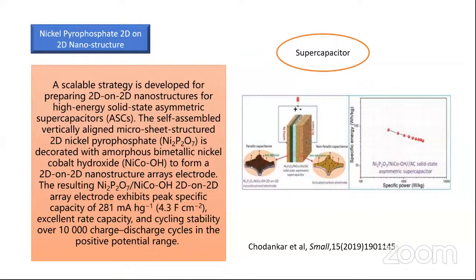The resulting nickel pyrophosphate, nickel cobalt hydroxide 2D on 2D array electrode exhibits a peak specific capacity of 281 milliampere hour per gram, and all these excellent capacities are given. And the cycling stability is over 10,000 charge discharge cycles. So this is a highly stable one, and it can go up to a large number of charge discharge cycles.